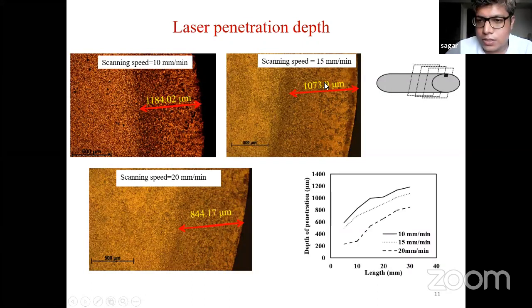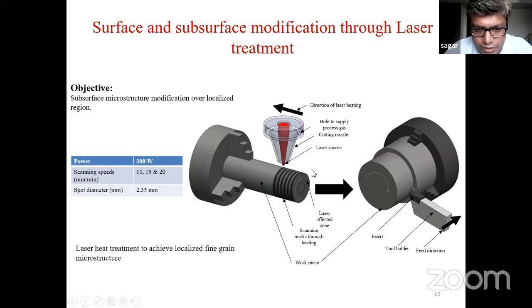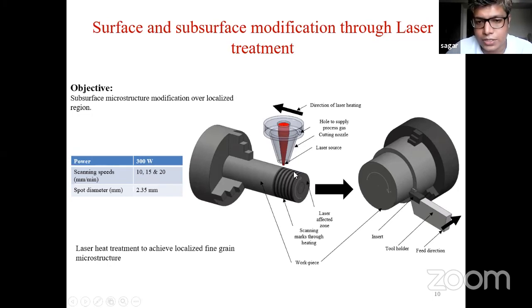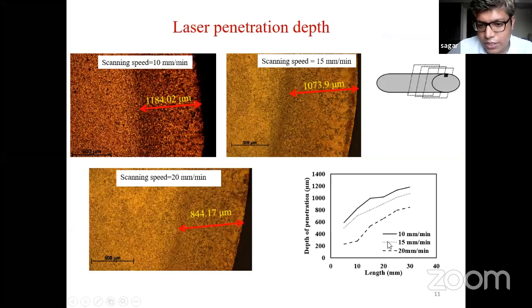Since as we move ahead on the sample with laser movement, the depth of penetration increases. This is because we give some overlap after each movement. Here you could see this is in a helix pattern. Your sample is rotating at a certain RPM, and accordingly the feed is provided to the laser treated sample such that the next laser beam will have an overlap of about 70%. That's why you could see the penetration depth increasing over the length of laser travel.